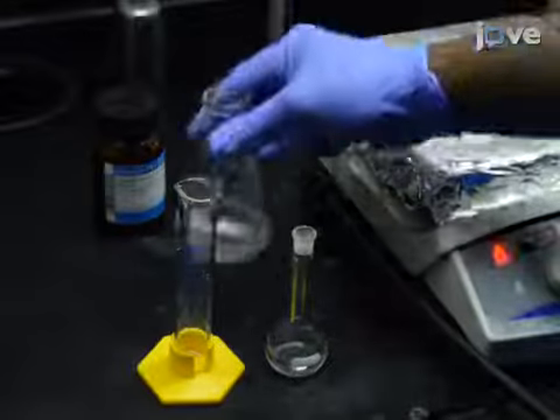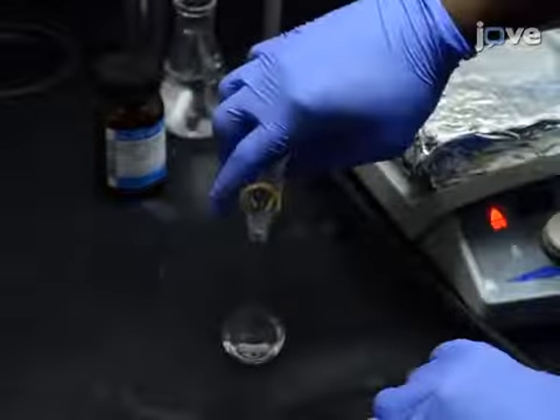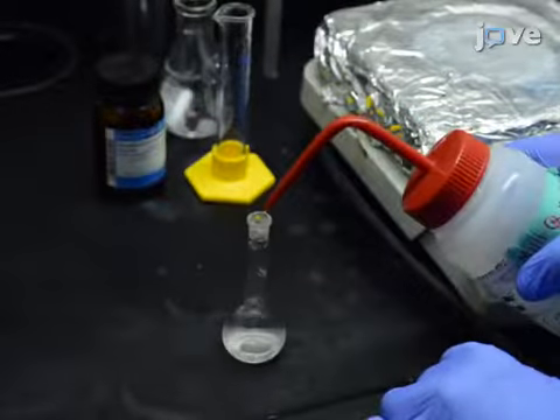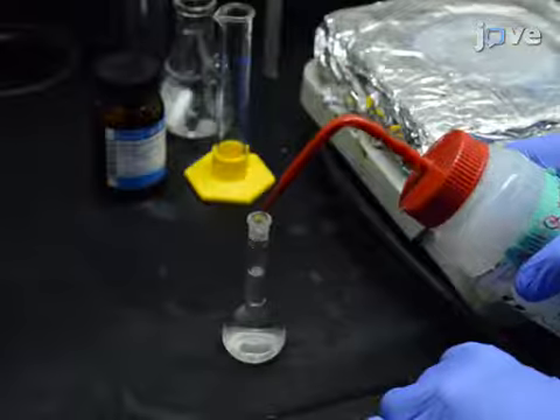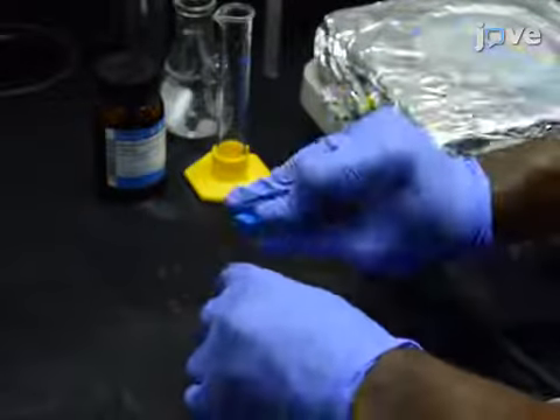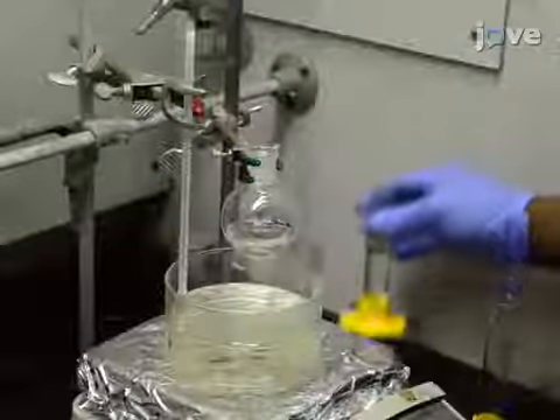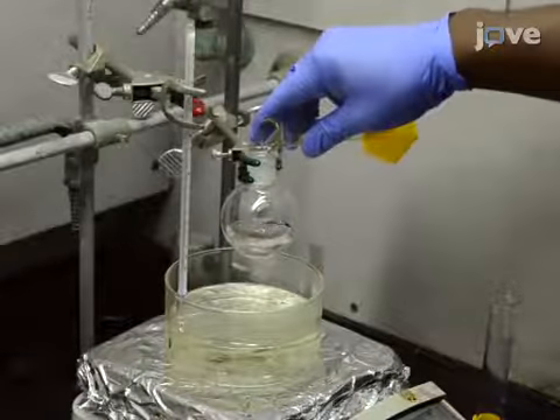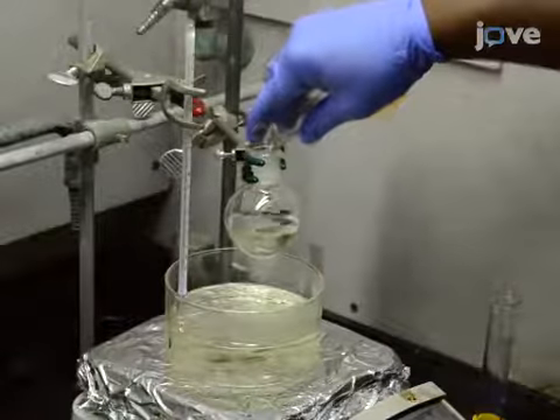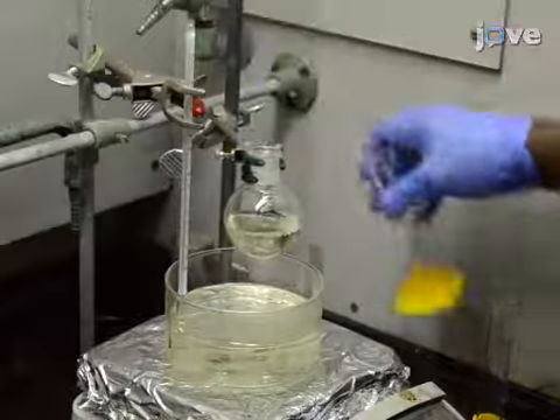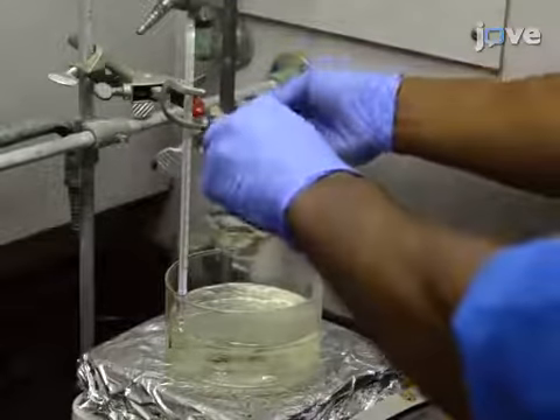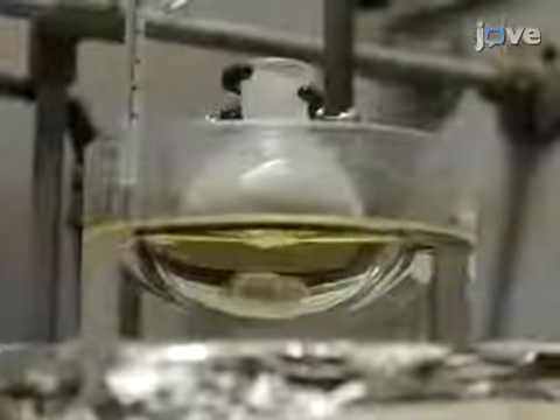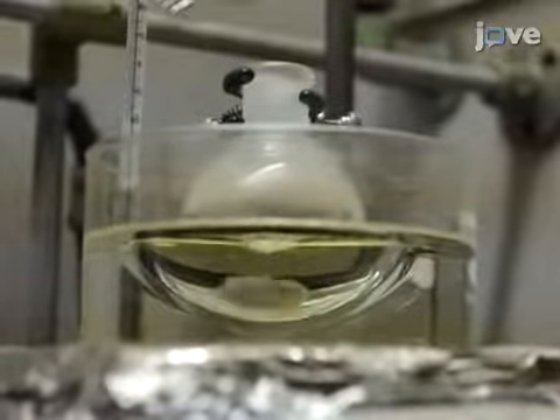Cool the mixture to room temperature and dilute to 50 milliliters with water in a volumetric flask to prepare a 0.2 molar CTAC solution. Mix 20 milliliters of 1 millimolar gold solution and 20 milliliters of 0.2 molar CTAC solution inside a round-bottom boiling flask. Allow to mix in an oil bath set to 60 degrees Celsius for 10 minutes. Next,